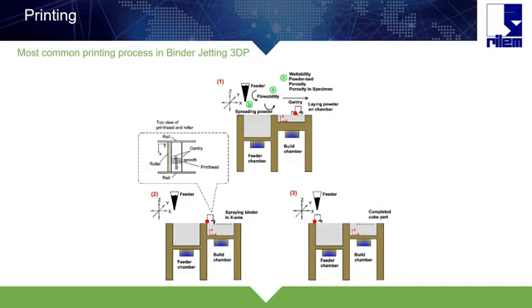We know the printing process basically consists of the following procedures to get the samples printed in a good shape. First of all, we need a feeder that holds the materials. After the feeder, the material goes through a flowability process and is spread into the back of the printer. Then we need a blade to send this material into the build chamber to make the powder layers on the chamber. And when the gantry comes, it has a print head that puts the ink on the specific area until we get the printed shape at the end.